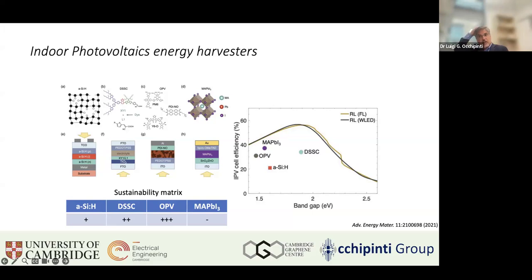And finally, lead-halide perovskite. Of course, you know better than me that perovskites have entered the scene very recently, but rapidly grown in interest. So they are the ideal candidate for high efficiency solar cells, both outdoor and indoor, reaching power conversion efficiencies higher than the incumbent technologies. However, the key challenge in lead-halide perovskite so far has been the limited photothermal and environmental stability due to the presence of the methylammonium cation, which sometimes can be compensated by other introduced barrier layers or control of the interfaces, or even considering different cations with better stability.